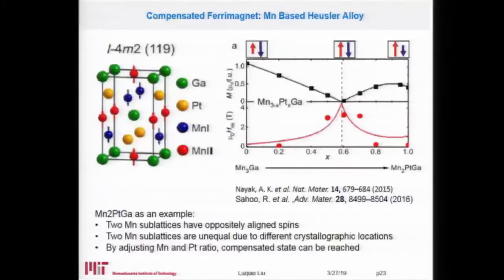Actually, people looked into this type of system like manganese 2, platinum, gallium. And they found that by varying the concentration between manganese and platinum, you can bring the total moment almost equal to 0. So for example here, X goes from 0 to 1, and you can see the magnetic moment goes to 0 when X is about 0.6. So you have 0.6 platinum and 2.4 manganese within the same chemical formula. This was studied a few years ago by Claudia Felser's group. And at this point, when the moment is very close to 0, you have a divergence in the coercivity, as shown here.